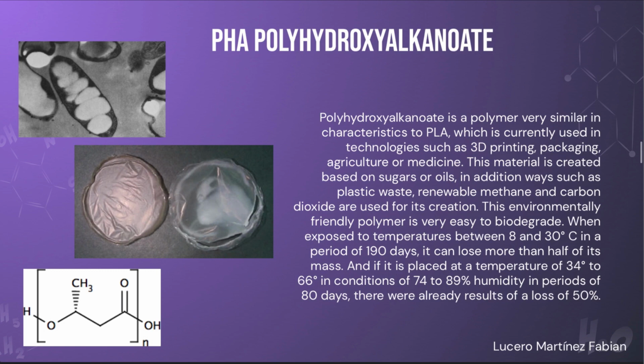But when these biodegradable polymers are exposed to temperatures between 8 and 30 degrees centigrade for almost 190 days, a mass loss of almost 60% was achieved, but with higher temperatures in intervals of 34 to 66 degrees in conditions of 74 to 89% humidity in periods of 80 days, there were results of a loss of 50%.